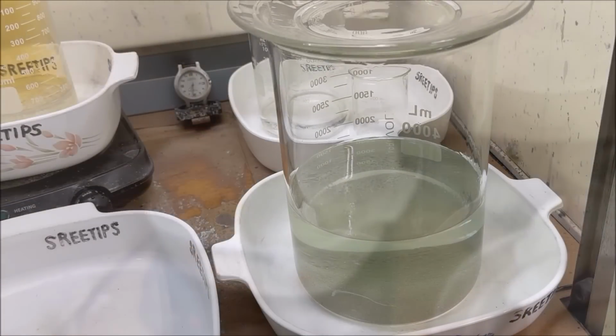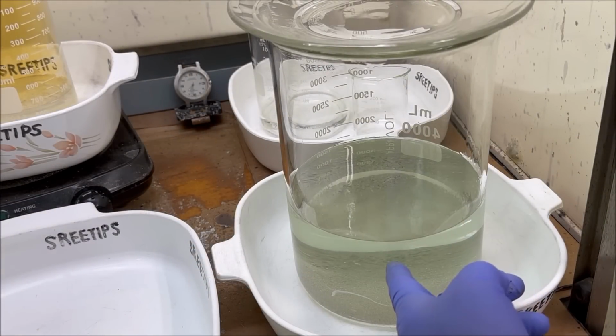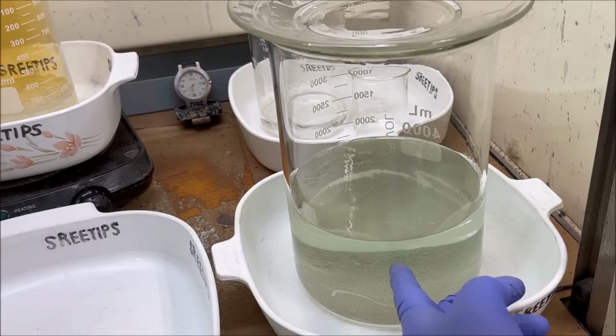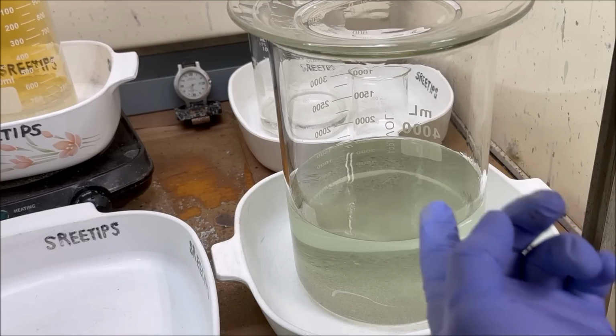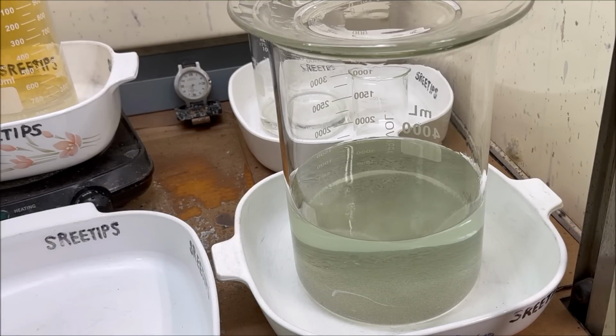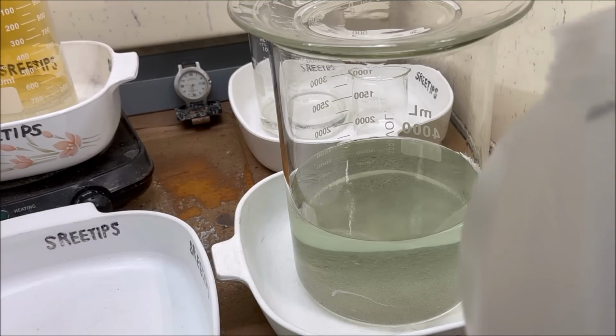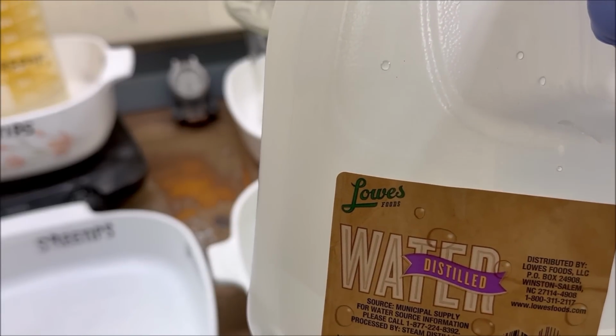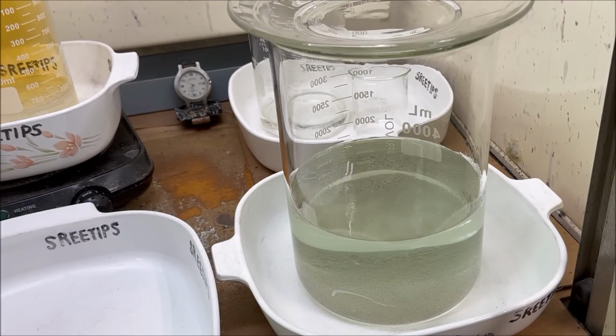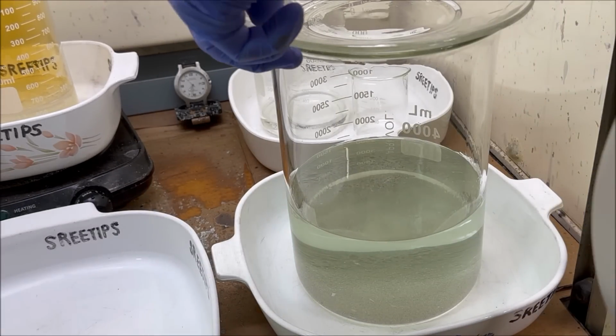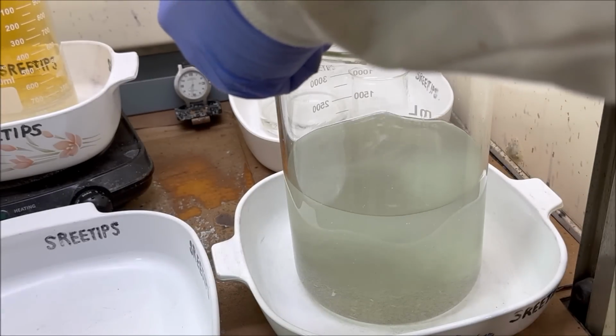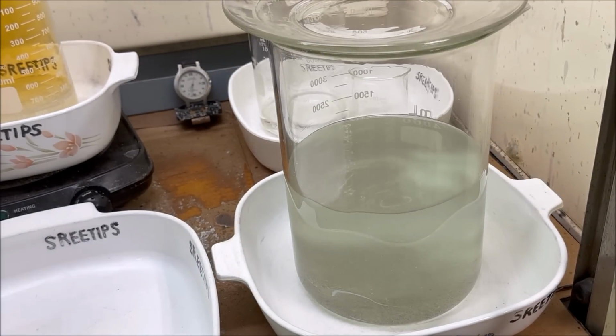In the meantime, I'm going to add some distilled water to this. This is about 1.3 kilos of pure silver dissolved in just about 1,500 milliliters of liquid. So I'm going to add some distilled water, because if I let this cool off, it'll form silver nitrate crystals. So I'm going to help prevent it from doing that by adding a little bit of water to this.